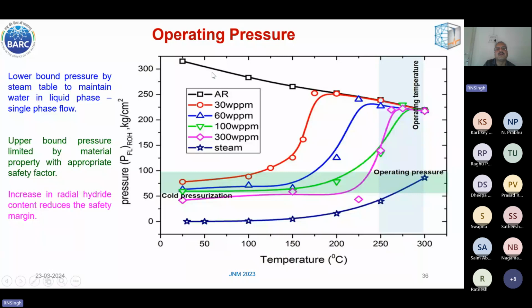So in case of the virgin material, you can see this solid line at the top. So you have sufficient safety margin. However, as hydrogen pickup takes place, hydride precipitates, and depending on hydride orientation, we will have these fracture toughness values getting reduced, and especially at the reactor operating temperature, this safety margin is getting significantly reduced. So especially radial hydrides, you can see here, these are all hydrides with the radial orientation, and you can see that the boundary provided by the metal property is coming very close to the operating pressure regime. So in such cases, these tubes cannot be operated. These tubes need to be retired.